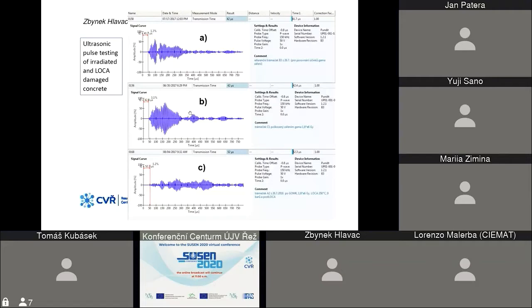Letter B shows the same sample. Oh, no, it's not the same, but it's from the same set of samples. And this sample is after gamma irradiation, about 2 megagrays. So you see that the time didn't change, not even the shape, the height of the amplitude didn't change. So that means that in this case, gamma irradiation didn't damage the sample.